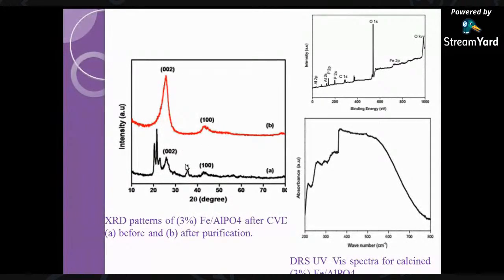Then when we do the experiment after CVD, you can confirm the formation of carbon nanotubes with respect to the study with XRD. Here, this XRD will give you proof that you can create carbon nanotubes over this catalyst. So this black spectrum represents the carbon nanotube with catalyst. Okay, so this has a combination of the carbon peaks, which indicate the 002 plane and 100 plane of carbon, in addition to a catalyst peak of iron. So after purification, when you remove this aluminum phosphate from the product, you end up with the final product, which is carbon. So we can extract carbon after acid purification.